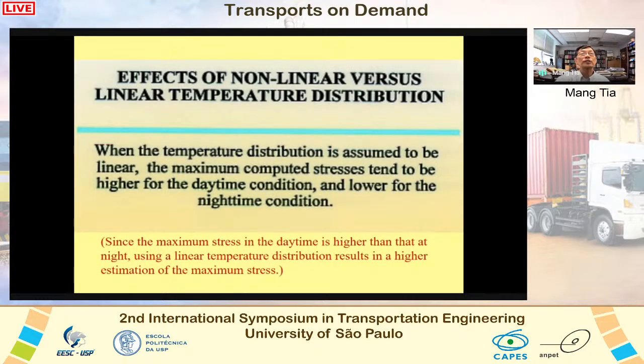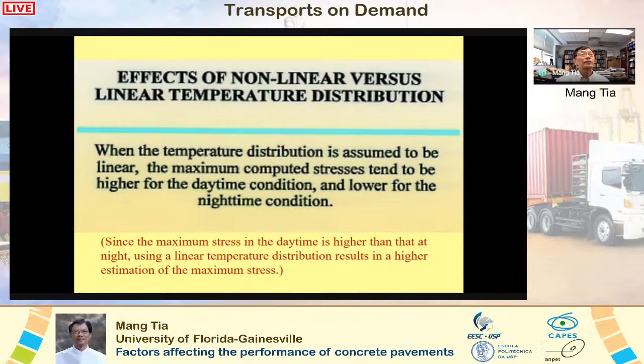Well, when the temperature distribution is assumed to be linear, the calculated maximum stress tends to be higher for the daytime condition and lower for the nighttime condition. The maximum stress in the daytime condition is usually higher than that at night. And thus, if we use a linear temperature distribution, we will get a higher estimation, which is a more conservative estimation of the maximum stresses. So it's okay to use a linear approximation, because in that way we'll get a more conservative estimate of the maximum stress.